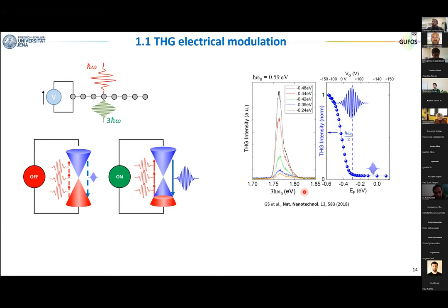So if you want to use a bulk material, you can never go on resonances. The problem is not for the fundamental photon energy, which is always in the transparent region. The problem is that if you now generate a third harmonic or second harmonic at a certain resonance, and then you propagate inside the crystal, the emitted harmonics will be reabsorbed by the material in a linear fashion. So basically at the output, you will get zero.